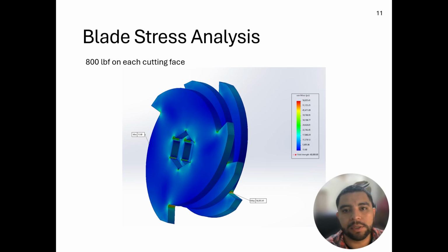After our initial design was done and our material was selected, we were able to use a static simulation in SOLIDWORKS to determine our max force of 800 pounds force, or 3,516 newtons per cutting face, before our material yields. Through our simulations, we also added circular cuts to each corner of our hexagon to reduce the stress where our blade meets our shaft.